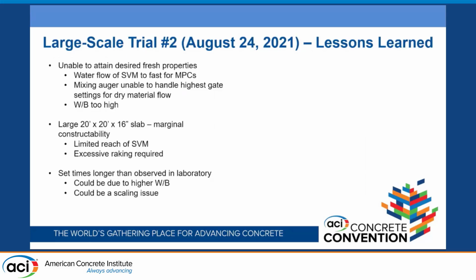So what we learned from it: this one didn't go well either, I'm going to be honest. We were unable to attain the desired fresh properties. Long story short, as I mentioned earlier, the water cement ratio for magnesium phosphates is a 0.2. Well, that simplified volumetric mixer is made for CSA-based cements, which run at a 0.4 thereabout. So we're getting twice the water that we needed. So the water flow is too high. The mixing auger was unable to handle the highest gate setting, so we couldn't get enough dry material into the auger to get the water cement ratio right. So therefore our strengths were not good. In fact, we went back a week later and our slab was still soft to the touch.